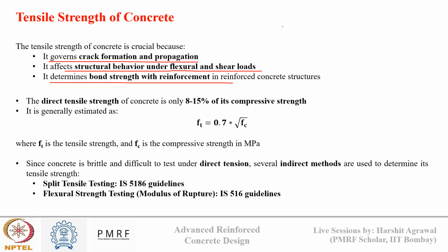Okay, so we saw when we talked about compression test of concrete, eventually it is the tensile failure that is occurring from the sides. And when we talk about reinforced concrete design, that tensile strength of concrete usually we neglect, but it is important because initial cracking is happening in the concrete only. And the bond strength with reinforcement, when the reinforcement is pulling out of concrete, then also there are tensile stresses that are generated inside the concrete. So we see when we increase the grade of concrete, the bond strength of reinforced concrete also increases because of higher tensile capacity of concrete.